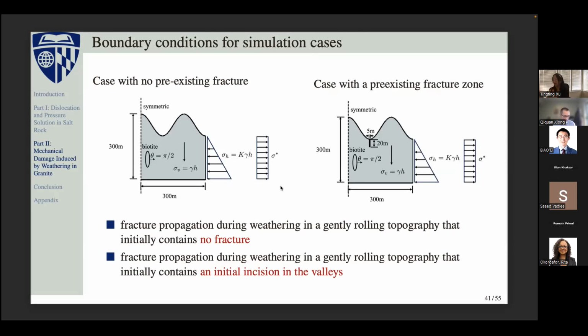So we have this geometry, and we have this applied tectonic stress, and we use that to initiate the fracture, and then the fracture will initiate the weathering. And on the right figure, we actually insert a pre-existing fracture zone, and this fracture zone will initiate the weathering, and then the weathering will degrade the stiffness of the solid, and then the weathering is going to propagate. So those are two different cases.